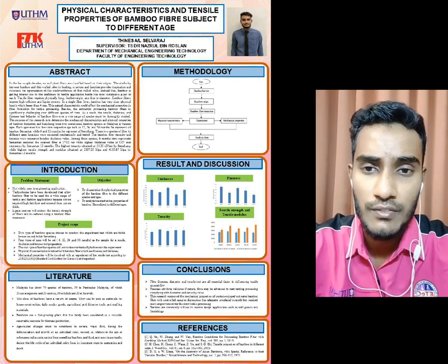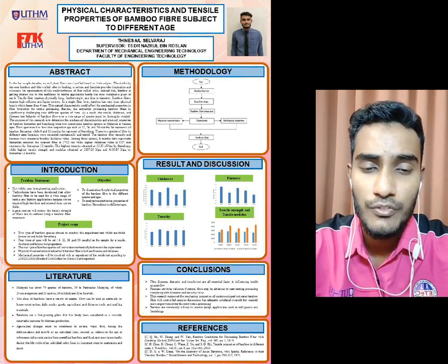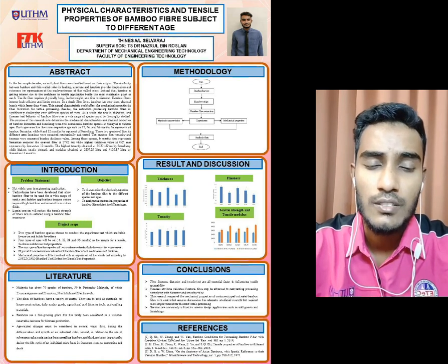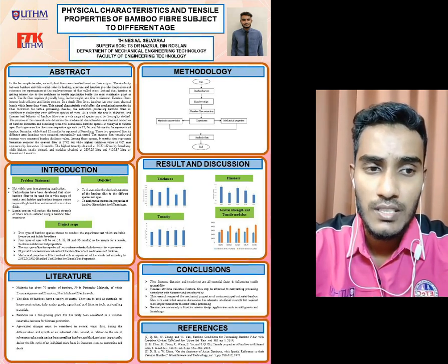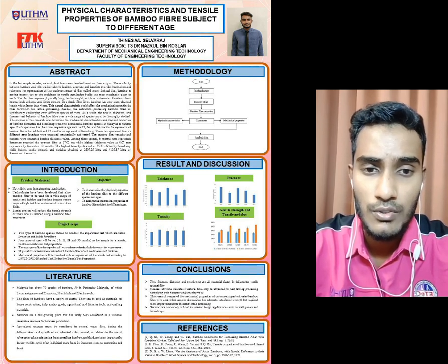It's because of the significant difference between the fiber diameter from 6 months to 36 months clump, which should be due to the effect of the stage, where they are considered as developing maturation. In fineness, the bamboo species of Semantan represented by SAM 12 has the higher value at 16.93, while SAT 36 is lowest at 16.44 tex. Furthermore, the bamboo species of Semalang for SAM 6 has the higher value at 17.02 compared to SAM 12. It's because of the different amount of sequential fiber within a strand of fiber, which contributes to a different mass value, resulting in the tex value.